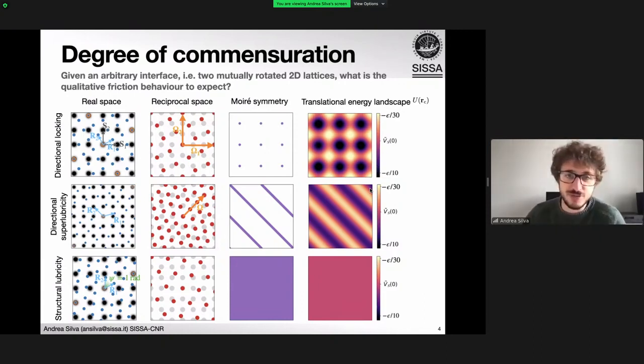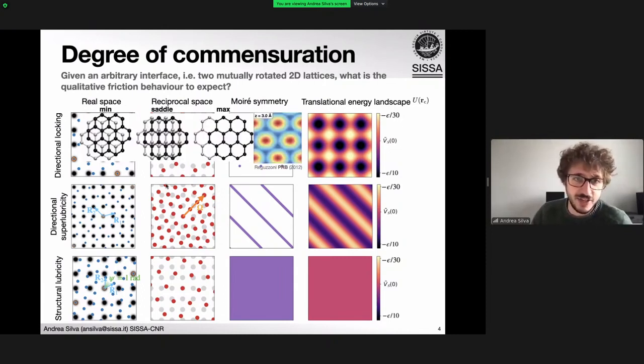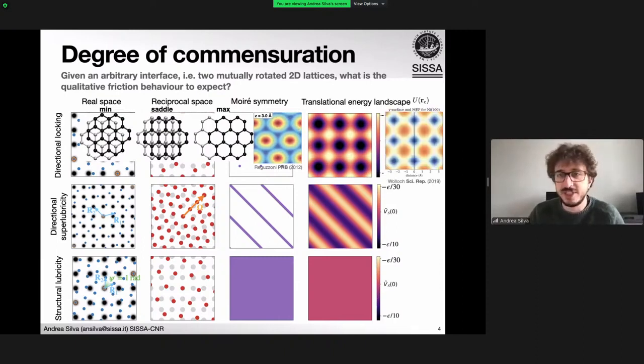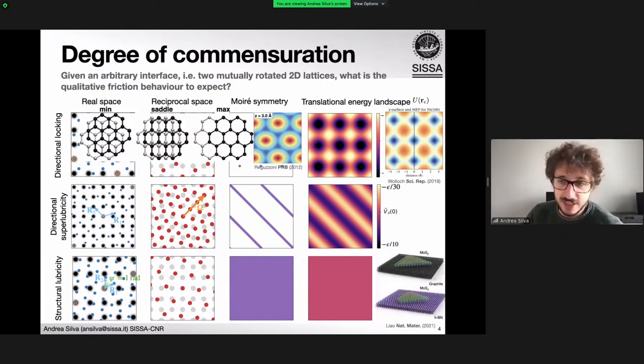And just to go a bit back to the real world, let's say, the first case would be the one of graphene sliding on graphene, where you translate the upper layer, you go through different configurations and you have minima and maxima alternating. Or an example with the same symmetry would be nickel on nickel. The case of structural lubricity would be, for example, molybdenum disulfide sliding on graphene or hBN, because they have a large incommensuration. And we are not aware of anyone reporting a theoretical study on this directional superlubricity with this specific friction anisotropy and the scaling law I'm about to show you.